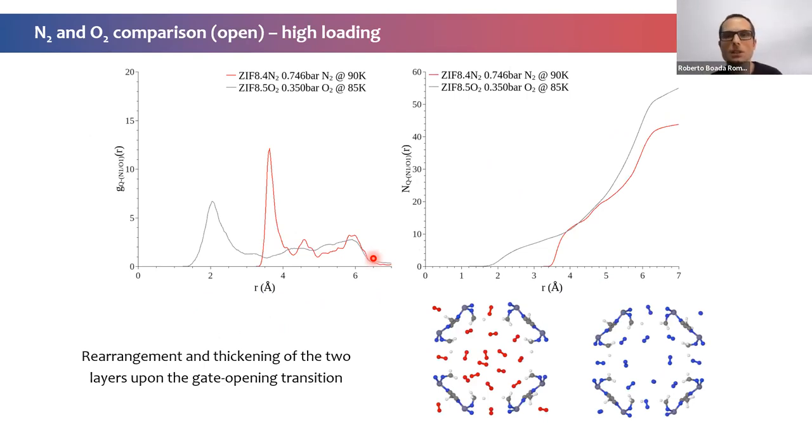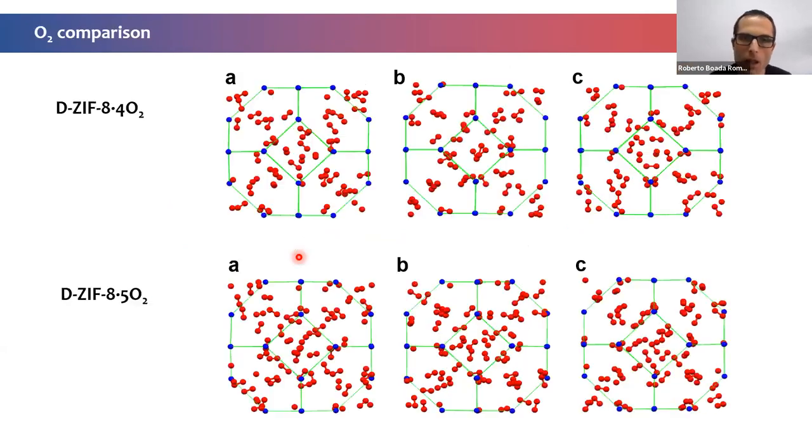when we increase the pressure, we go across this gate opening transition. The oxygen is still distributed in two layers, but both the nitrogen and the oxygen are distributed in two layers. But the case of the oxygen is more complex in the sense that it's broader. So it does not go into the center of the pore, but expands a little bit more. And this is, for example, for the case of the oxygen,